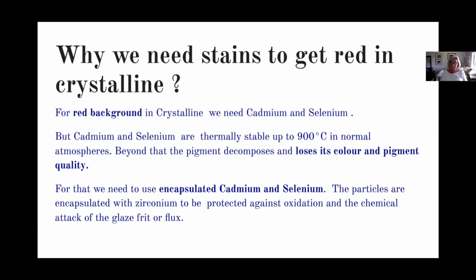For a red background crystalline, we need cadmium and selenium. But cadmium and selenium are thermally stable only up to 900 degrees. Beyond that, the pigment decomposes and loses its color and pigment quality. For that, we need to use encapsulated cadmium and selenium. This is why you must use stains to get reds in the background.